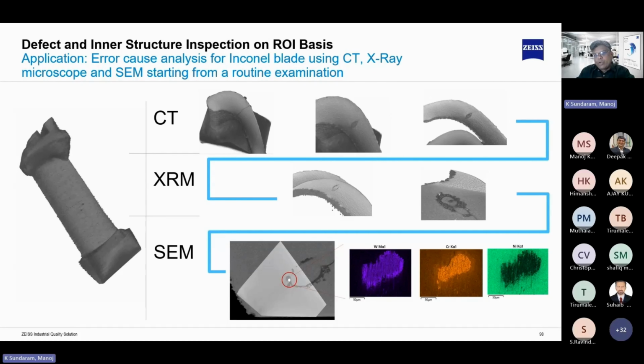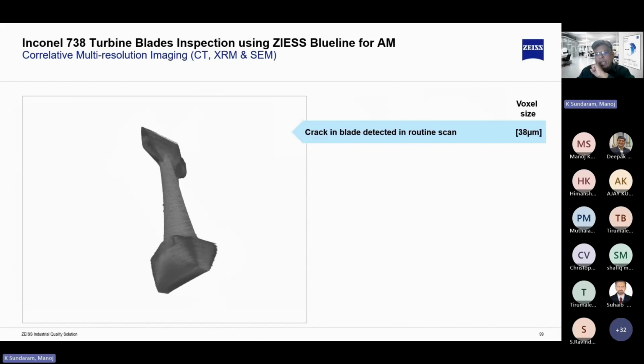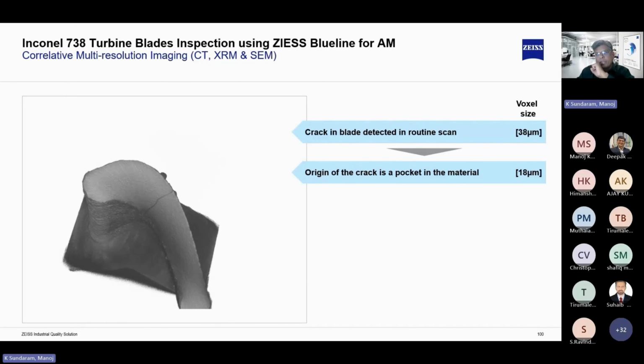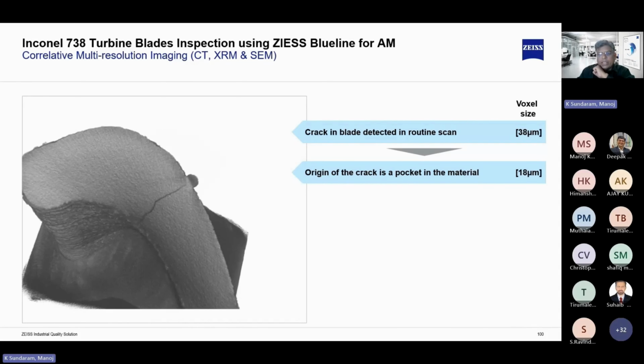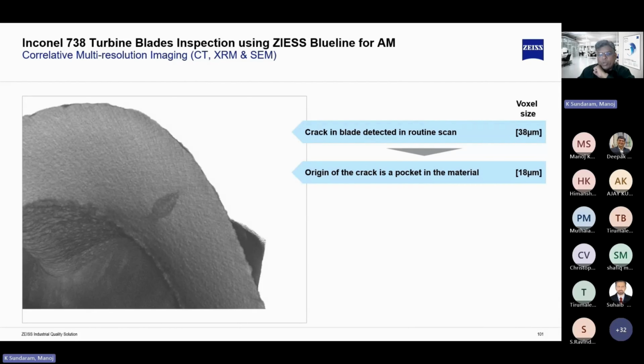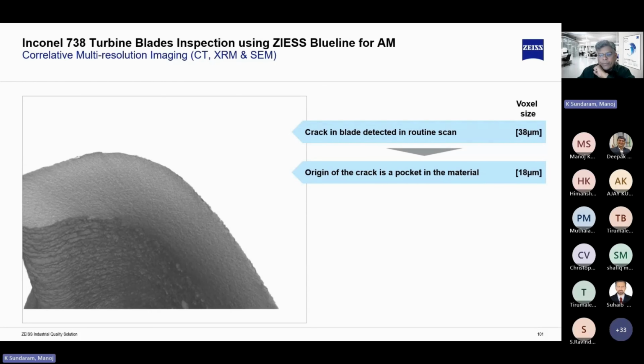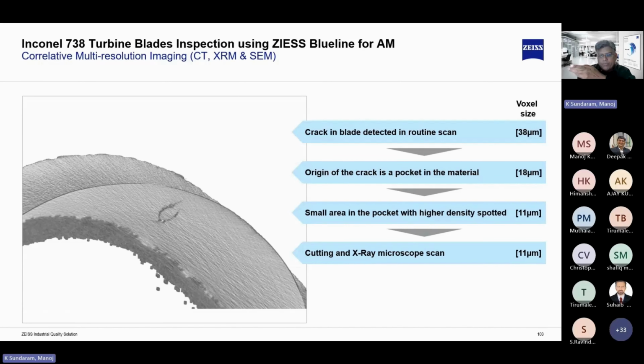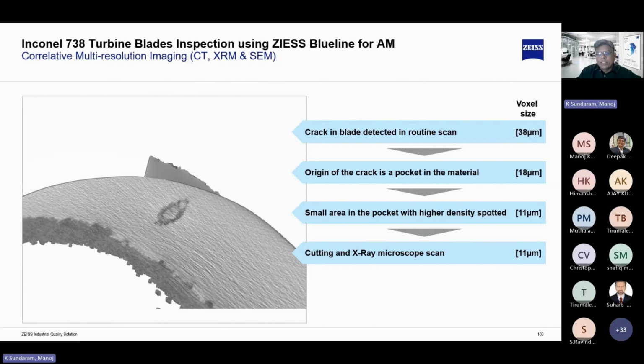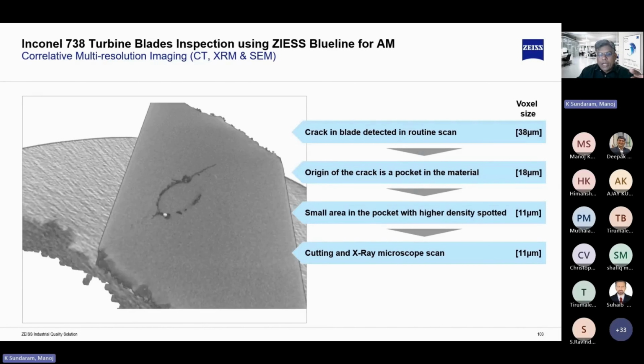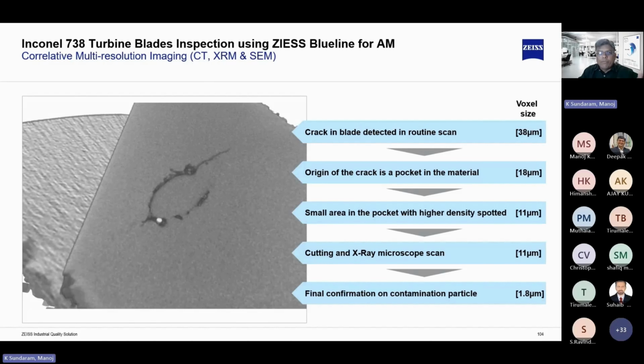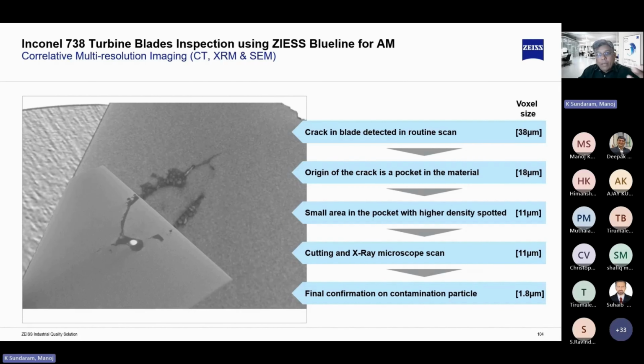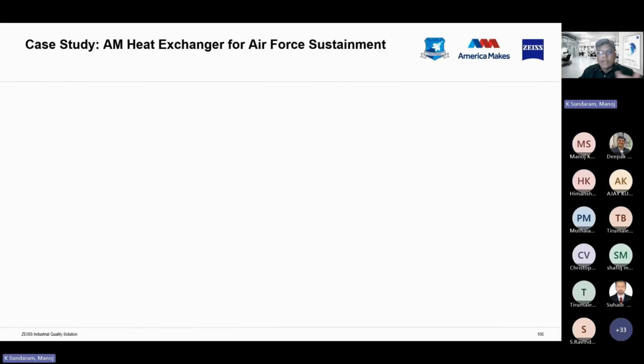You do a CT, then you look at that and say, okay, there is a crack I can see at a certain location. Can I do a finer measurement at 18 microns? Oh, now I see it in a little more detail. Can I get a little higher resolution to see what is going on there? Then I go down to 11 microns. Fine, good enough. Now, can I cut it and put it in an X-ray? Why has it cracked? What you see here now is a highlight, a material with a white spot. That white spot is a foreign body which has come in there. We will have to confirm what the contamination particle is in a microscope, as Mr. Parani explained in his presentation.